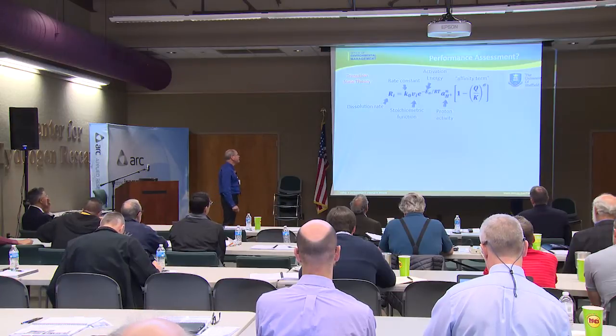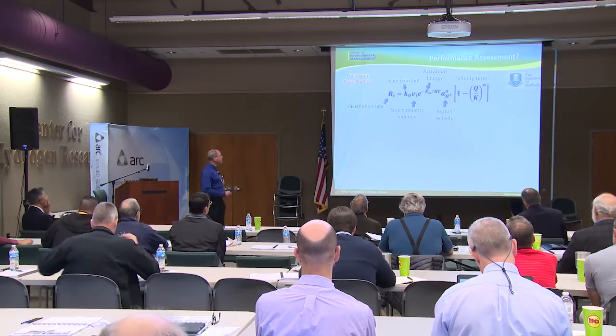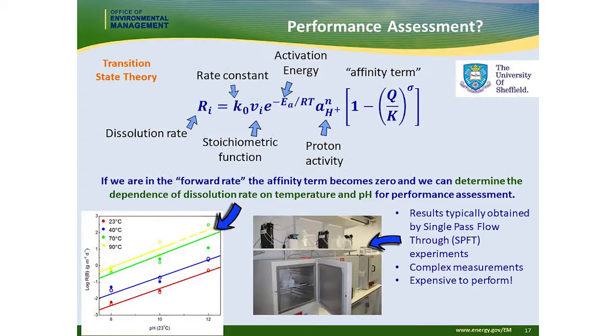So if we look at this from transition state theory, well, you've got the different terms, the rate constant, activation energy, the proton activity, which is our pH, fits into there, an affinity term, which actually gets set to 0 if we're in the forward rate. And if we look at this at different temperatures, typical log pH plots, then what we see is we can determine the dissolution rate dependence on temperature and pH. This was for early testing on other glasses.